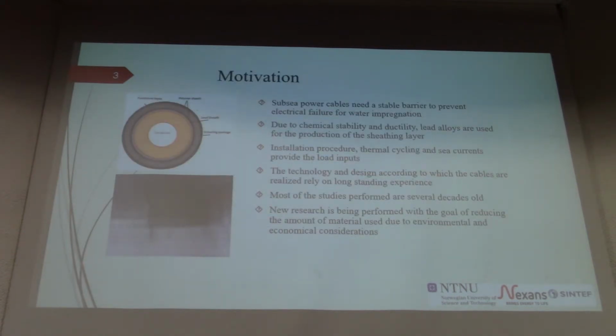So in subsea power cables, to prevent the cable from failing from electrical short circuit, we need a watertight barrier. And what is used is a very, very ductile metal layer, because it's stable and it's watertight. And that is, in this case, lead alloys. This is not a new technology, it's quite old indeed, but most of the work was done several decades ago, and now there is a new interest from this industry to try and understand if it's possible to reduce the amount of material due to economic and environmental concerns mainly.